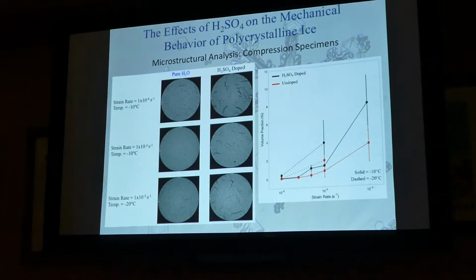And we saw differences, which was interesting. So the sulfuric acid doped ice, if you want to see it on the plot, it's here. If you want to look at it in the pictures, it's here. The sulfuric acid doped ice had more cracks than the pure ice. And you saw that at all the different strain rates at different temperatures, and the cracking started sooner. So the sulfuric acid seemed to make the ice weaker in compression, and also for the cracks that did occur, it made it so that the ice was more easily able to start cracking.